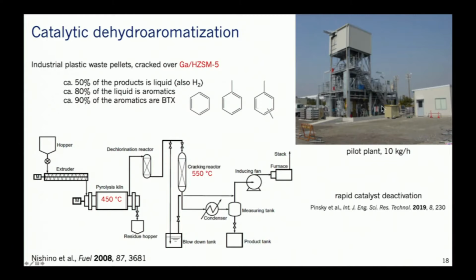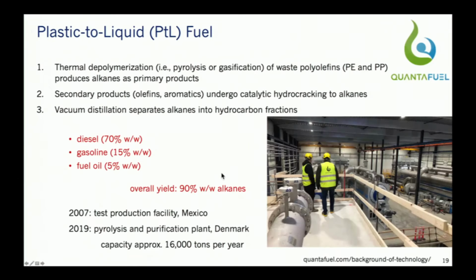And this process actually led to the construction of a pilot plant to show the viability of this process. Unfortunately, it didn't last very long because of very rapid catalyst deactivation at these very high reaction temperatures. But people have continued to work on this. There's an announcement very recently from Quantafuel in partnership with BASF using thermal depolymerization followed by catalytic hydrocracking, that means in the presence of hydrogen, to give alkanes, and reporting very high yields of alkanes over the range from diesel to gasoline to fuel oil. And this is scaling up at the moment in Denmark.